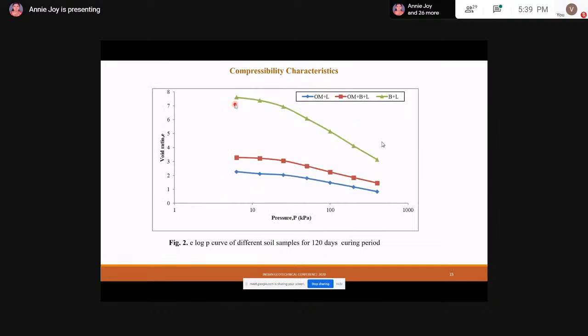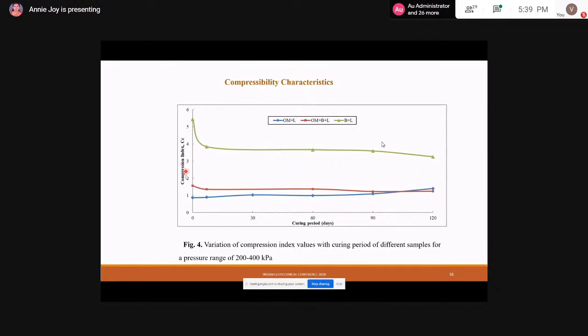Here also we could see that as the organic matter content increased, the void ratio decreased, which led to the increase in compressibility. Now this is the variation of compression index with curing period. Here also for bentonite plus lime soil mixture, we could see a decrease in trend, but as the organic matter increases, you could clearly observe that at the end of 120 days, the compression index started increasing.